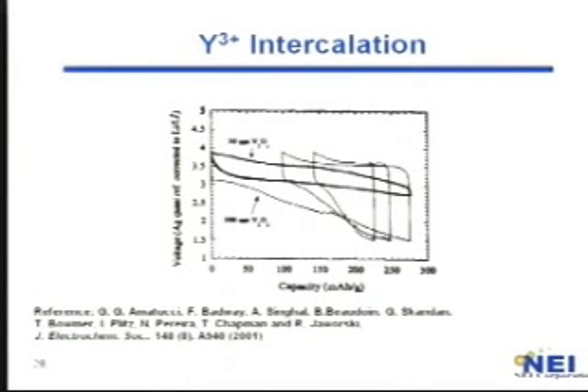And this is actually a published paper. We worked with Glenn Amatucci at Rutgers. Here, when you take 500 nanometer vanadium oxide, the material loses its capacity and its reaction is absolutely irreversible. While when you go to nano V2O5, 50 nanometer, this is the discharge profile, and it is absolutely reproducible, absolutely reversible.